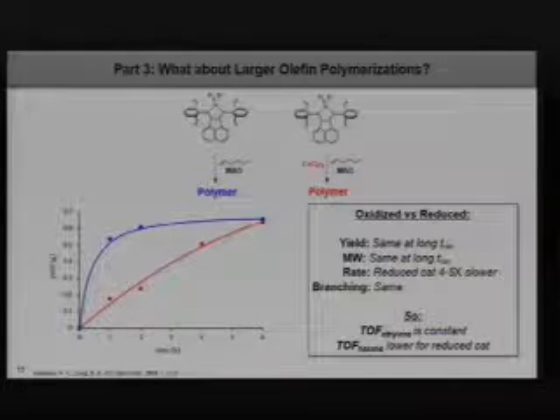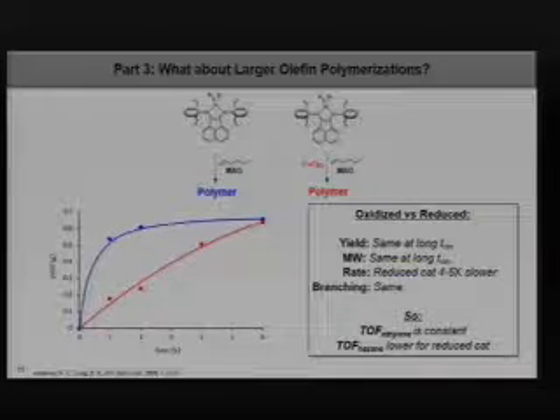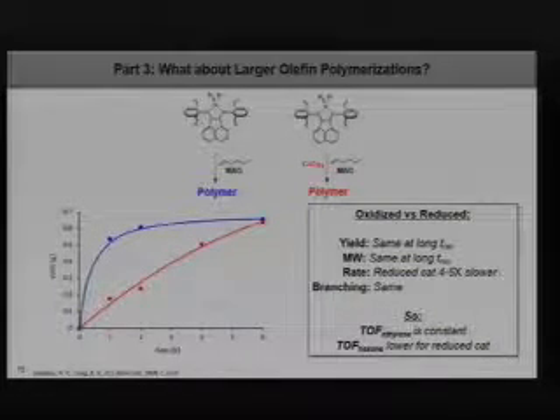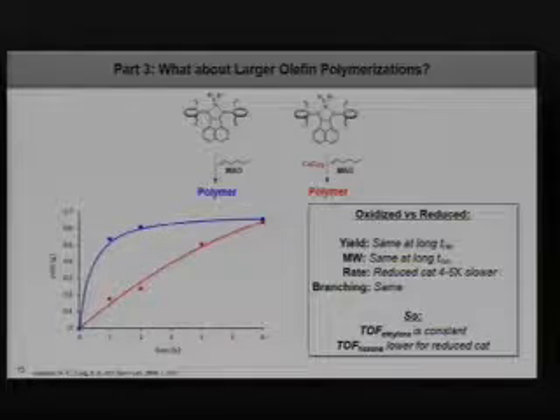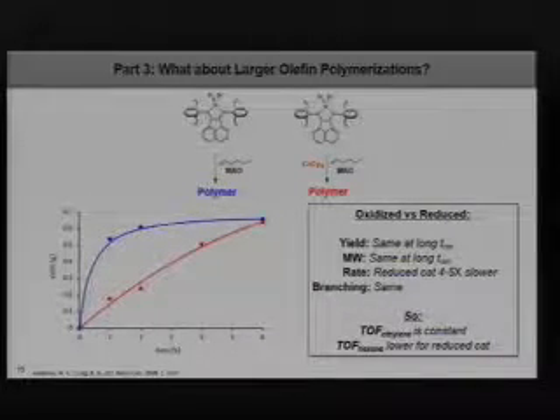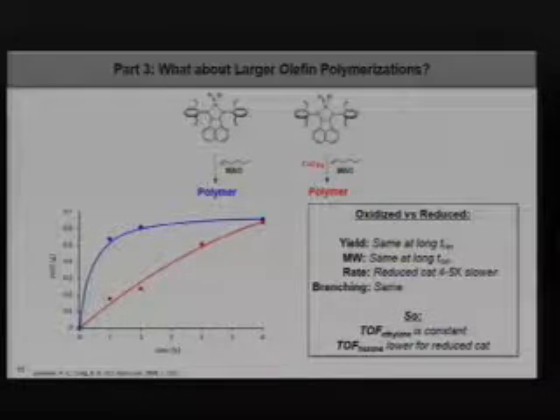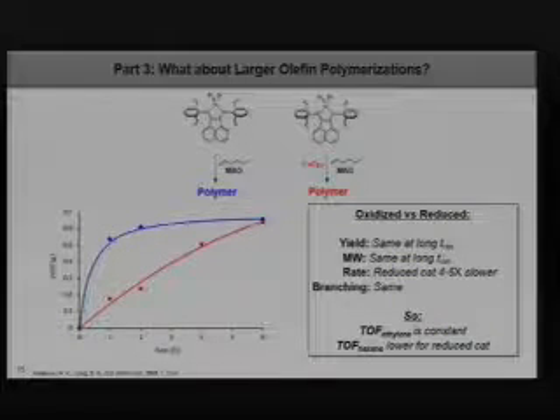And if we analyze the polymers in each of these cases, the yield was the same, the molecular weight was about the same, the branching was the same. These are all very hyperbranched structures. But the rate had dropped significantly. So we thought, okay, the turnover frequency with ethylene we knew was constant from our previous work, but the hexene is significantly lower. So what happens if we copolymerize these two things together, and can we still get the same results?